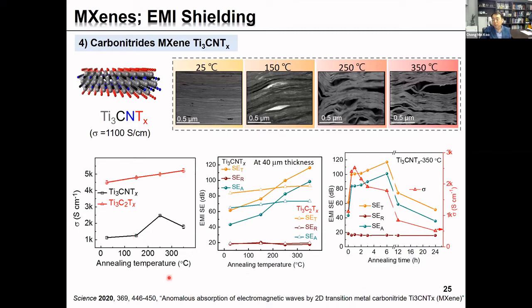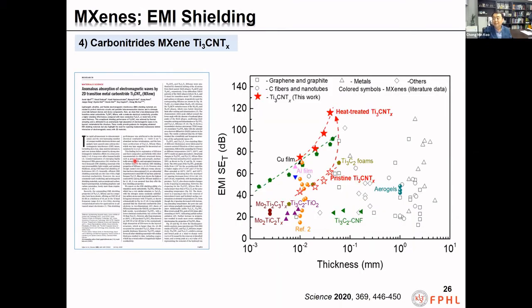An interesting point is that the improved total shielding effectiveness is mostly caused by improved absorption property, since the shielding by reflection is rarely affected by the heat treatment. In an optimal condition, Ti3CN revealed 116 shielding effectiveness at 40 micrometer thickness. The heat-treated Ti3CN carbonitride outperformed all the shielding materials, even the Ti3C2 MXene.